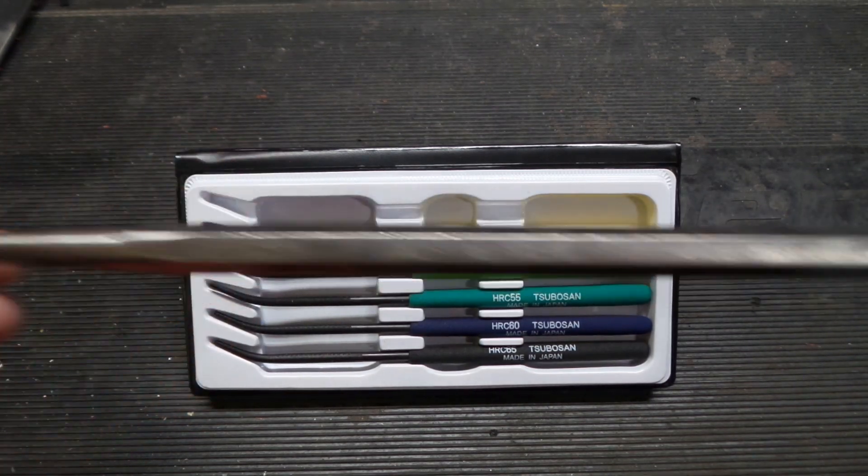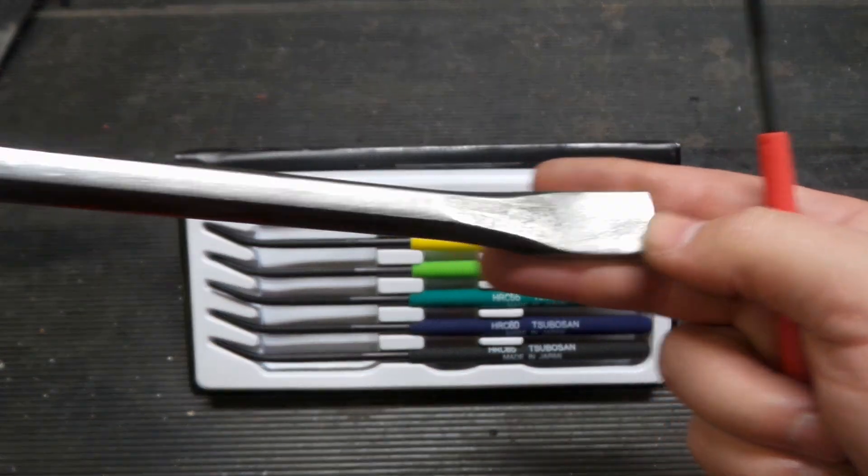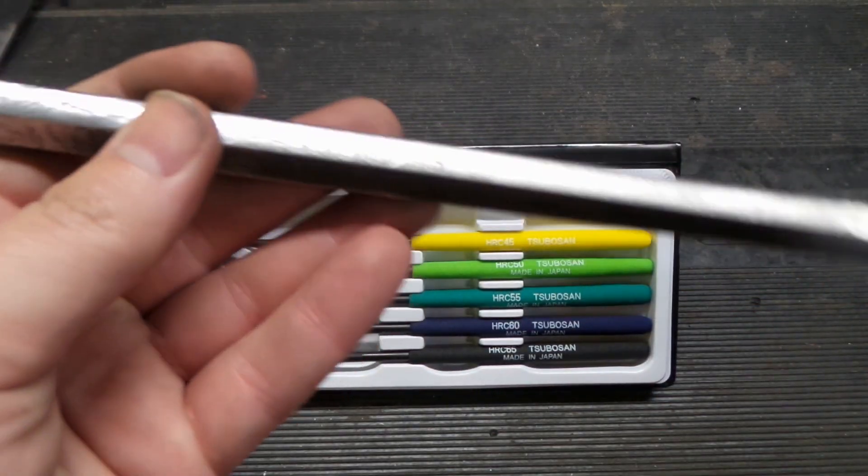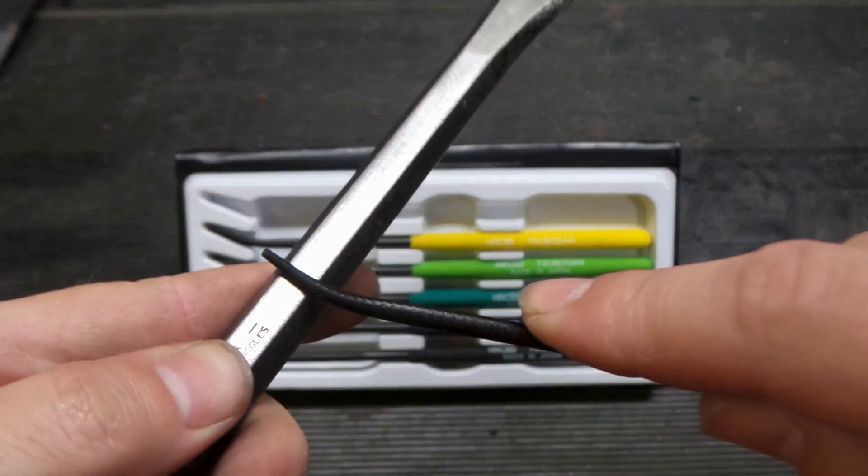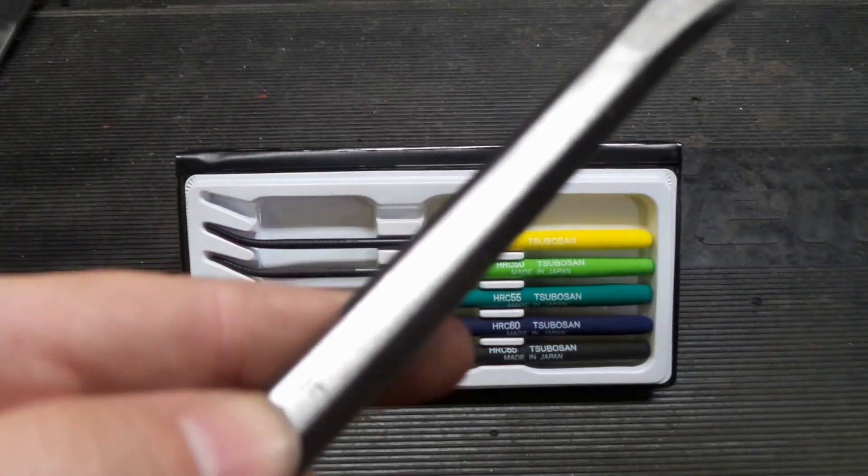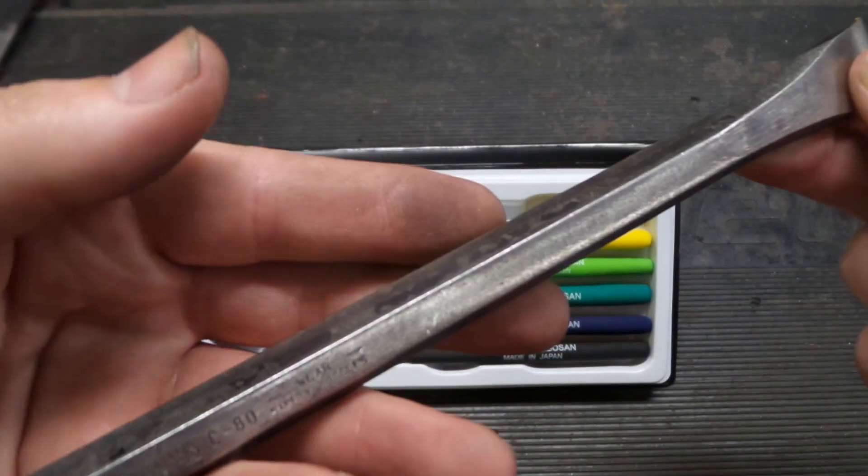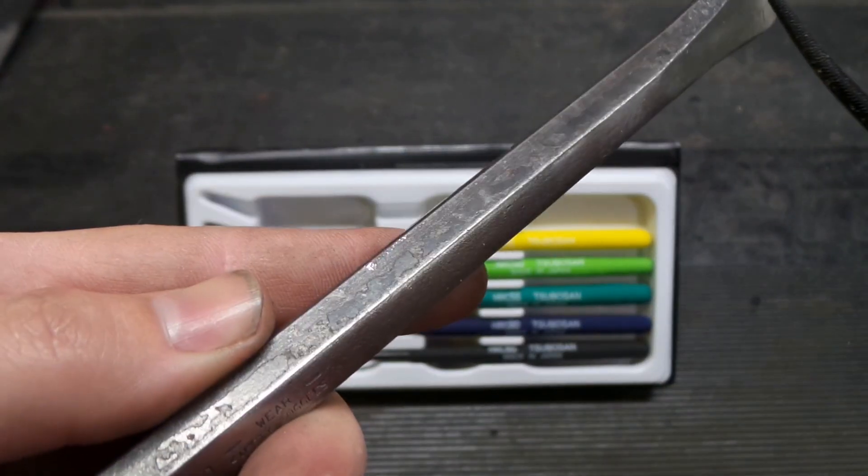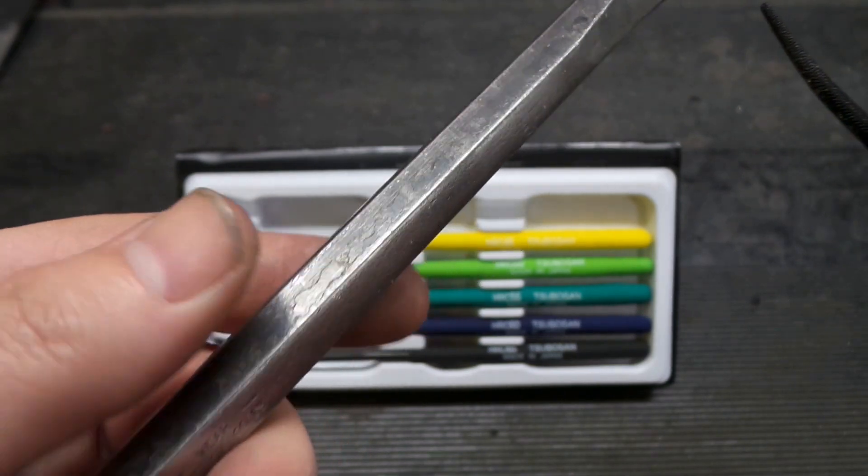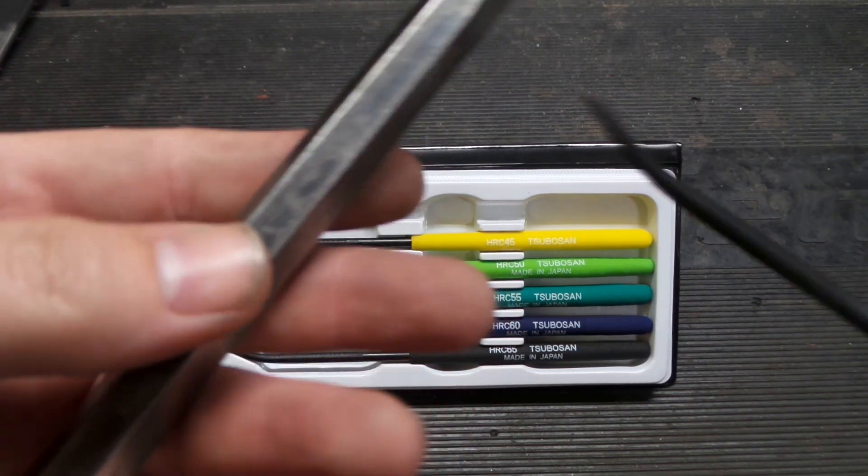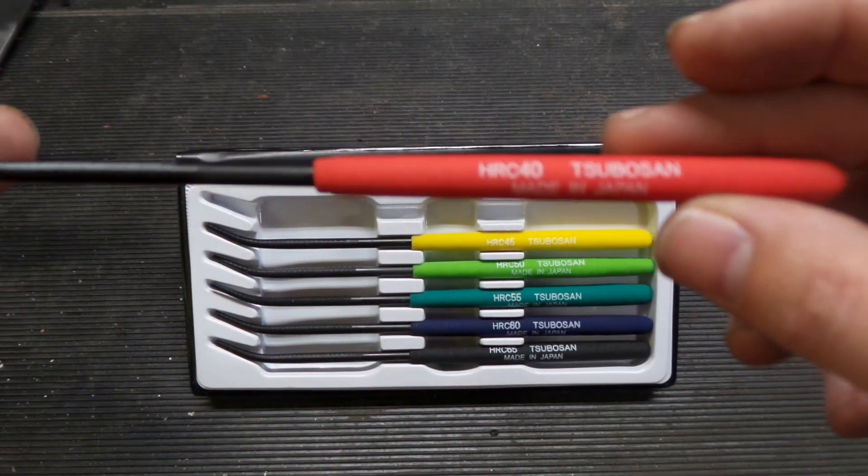Let's take out this old Williams lining pin here with a pry bar on it. And I think this pry bar end might be hardened, but I don't know that the handle is. So let's see here. Yeah, you can see we definitely scraped into it there. That wasn't super easy that it dug in, so that's probably right around 40 Rockwell.